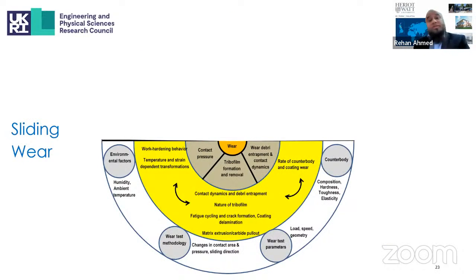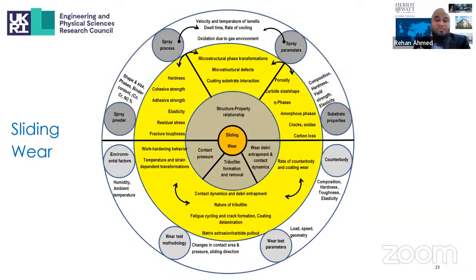So in terms of the tribological test conditions, test method and test parameters, such as the material of the counterbody, the load, the speed, direction of motion, and the environmental conditions, they all play an important role in the sliding wear process. And the selection of these parameters influence the contact pressure, the formation and removal of the tribofilm, and the entrapment of any wear debris, leading to three-body abrasion within the wear track. However, these are all dependent on what method you have used for the measurement of wear. And that's only half of the story, because the other half of the story lies with the selection of the coating process parameters, and the characteristics of the powder, which all influence the structure property relationships.